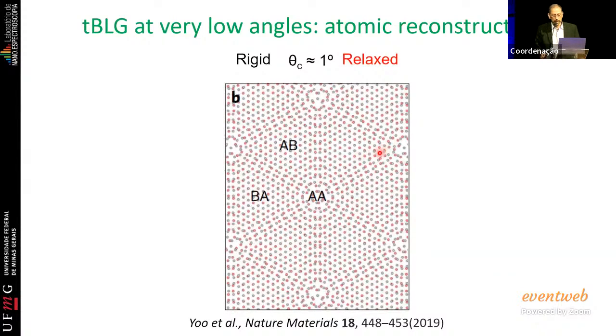So what you will have is triangular shaped areas of AB stacking, but because the region that was here rotates to get to the stable situation, it rotates in one direction, while nearby, it rotates in the other direction. This happens with the formation of a domain wall. This is a place where you have a strong strain and the stacking is not there, okay? So this is the reconstructed twisted bilayer graphene at very low angles.